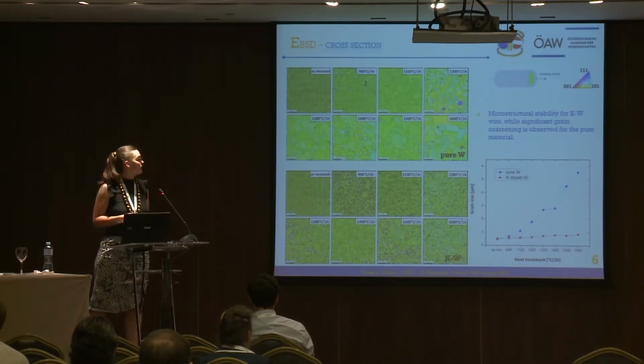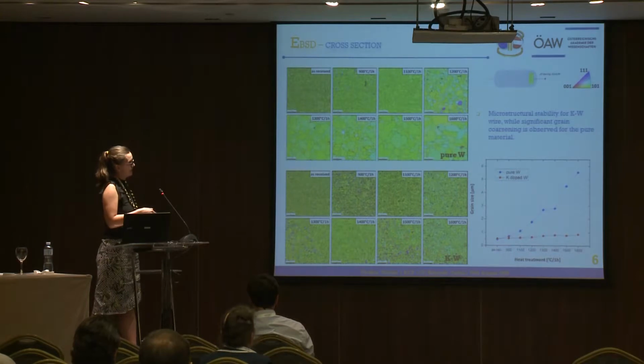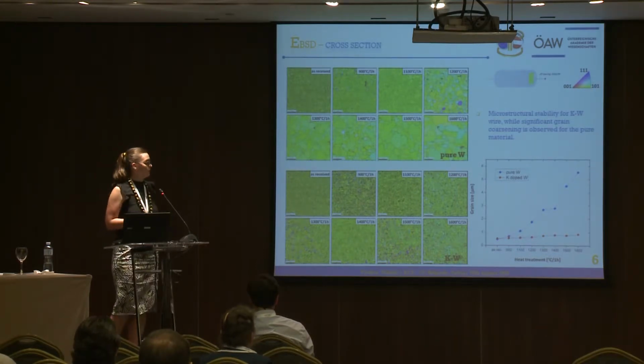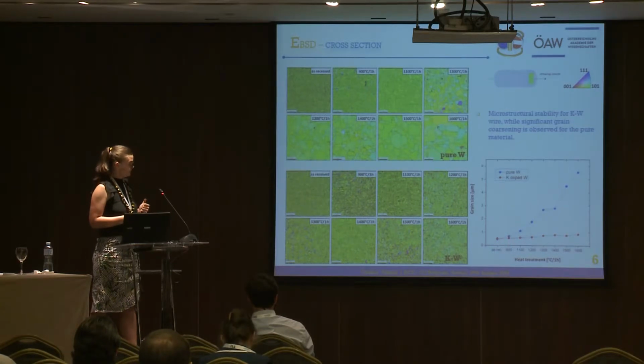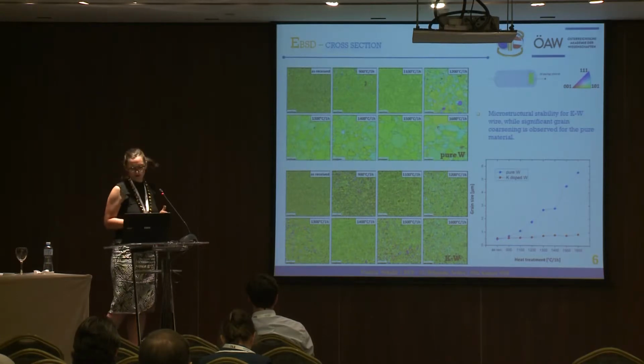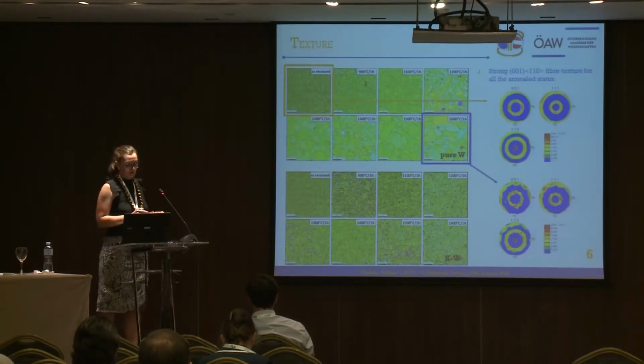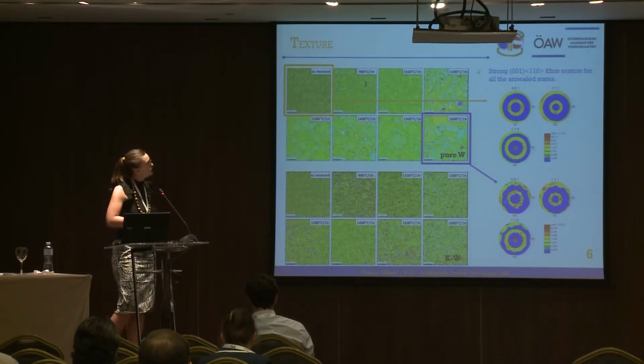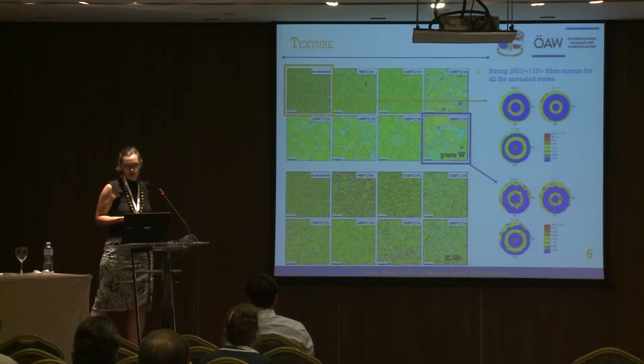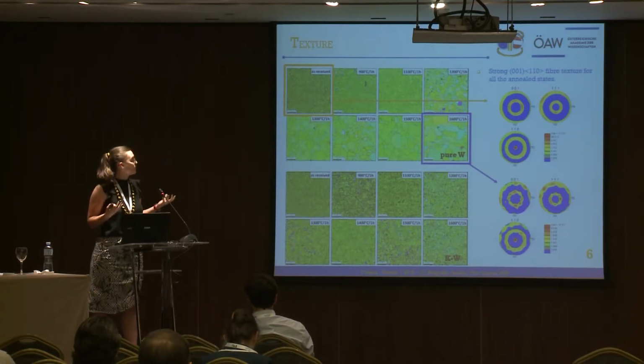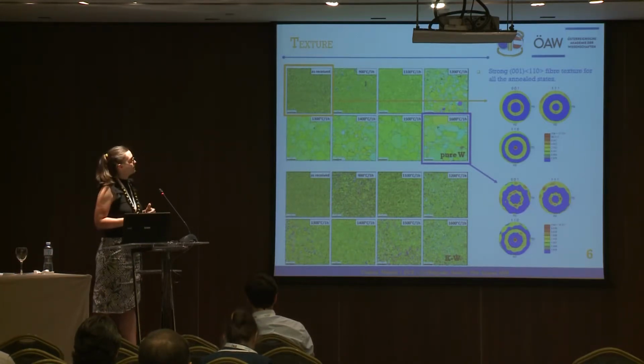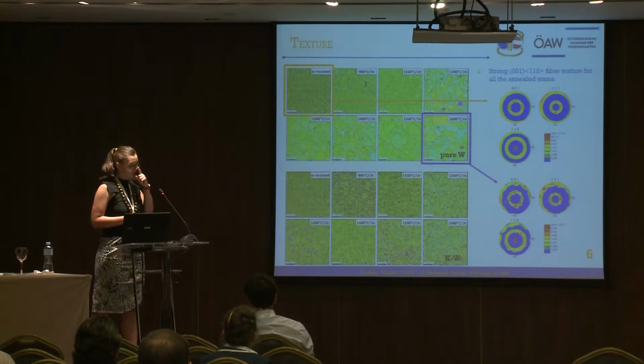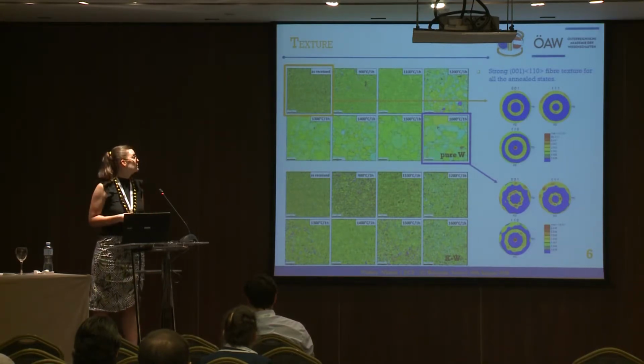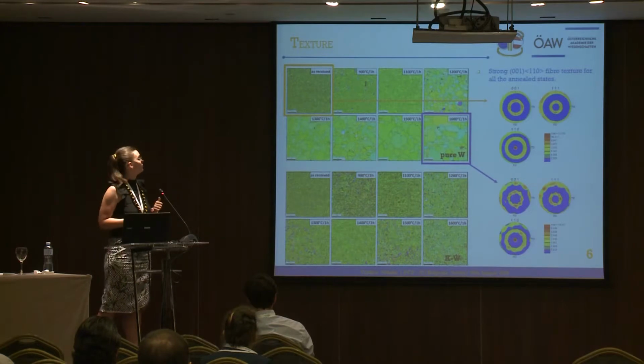So we can determine the diameter of the grains and see to what extent it increases at the highest annealing temperature. In the case of potassium doped, there is a slight increase, but incomparable to the undoped material. The very green color is an indication of a very strong texture. This is, again, a result of deformation during production. It is the so-called fiber texture with a very pronounced 110 direction, and when looking at different annealing states, we can see that this texture is preserved through various heat treatments.